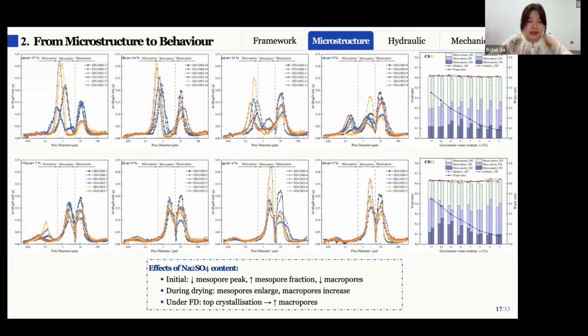And the influence of sodium sulfate becomes mainly evident at the later stage of drying and can be understood in 3 steps. First, at the initial stage, increasing sodium sulfate content leads to a reduction in the initial meso peak. And as the drying proceeds, the pore size continues to evolve and the size of mesopores increases, but their proportion gradually decreases. And finally, the drying mode plays an important role, because under slow drying, sodium sulfate crystallization remains relatively uniform. In contrast, under faster drying, crystallization is concentrated near the top of the sample, which leads to a local increase of the macropores.